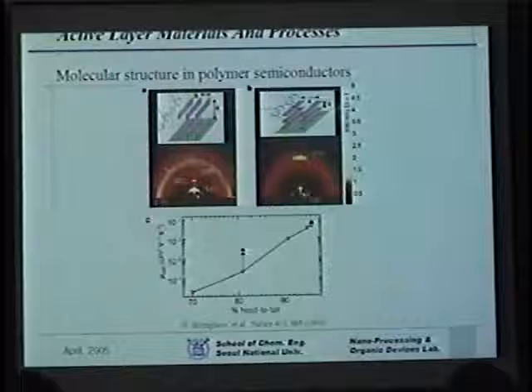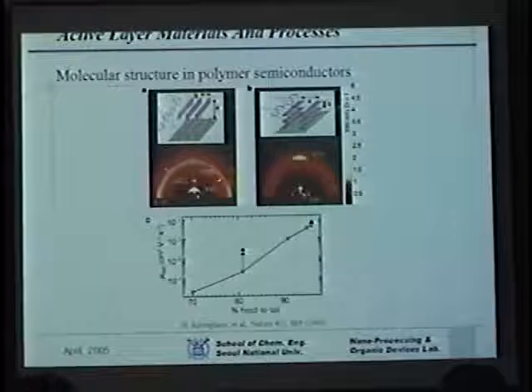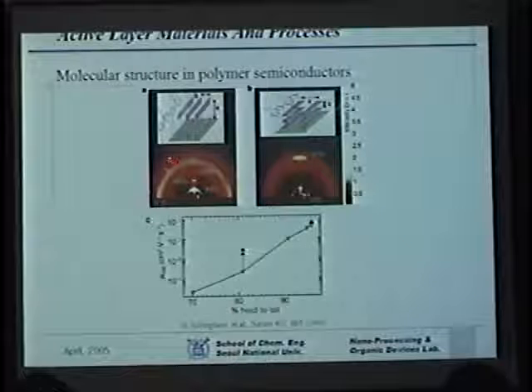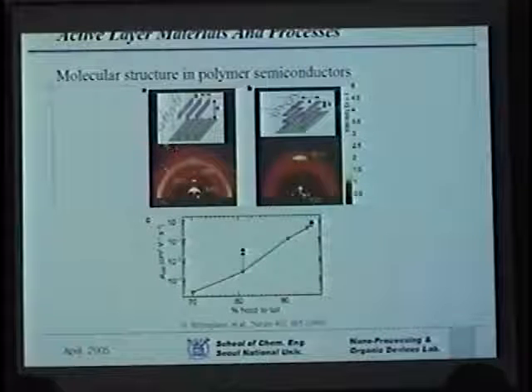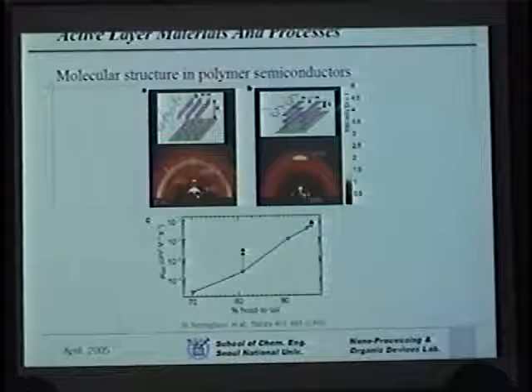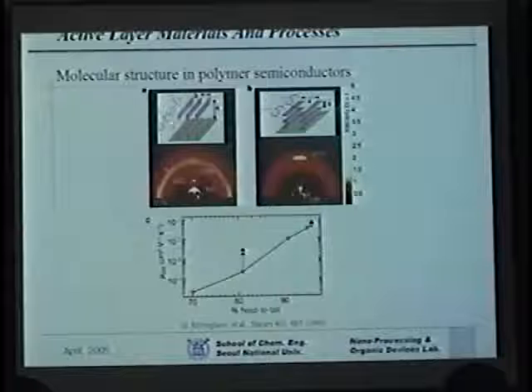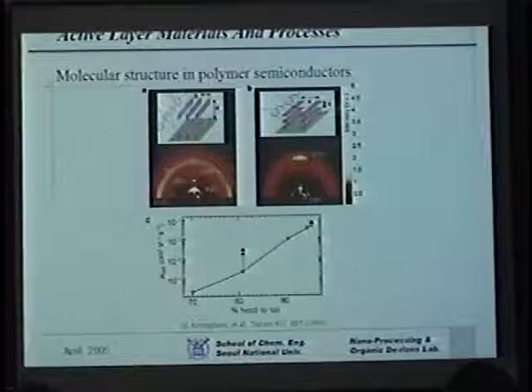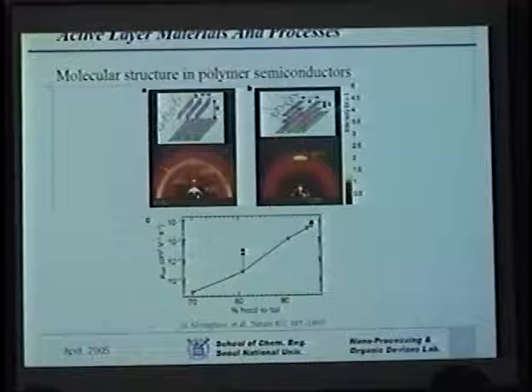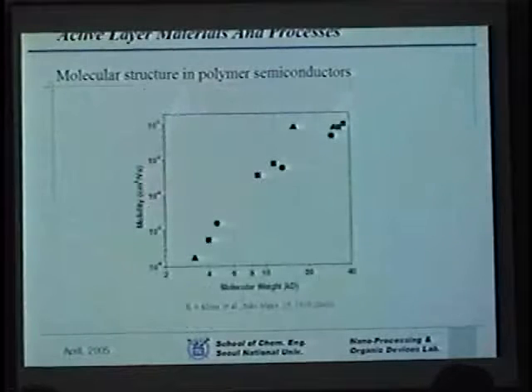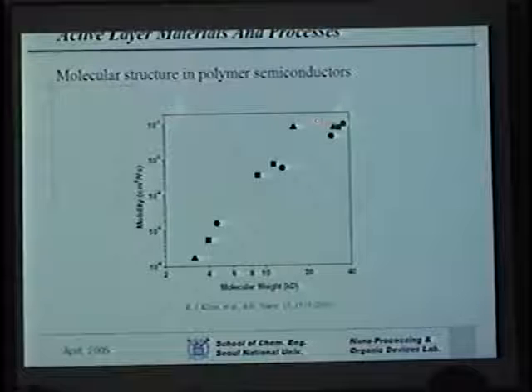Also shown here is the effect of molecular structure in the case of polymeric material. And it has really to do with the regularity of the molecule. For instance, if it's aligned this way, and the pi bond here overlaps with that one, there's a natural conduction path here so that electrons can flow fairly well this way. But if it's stacked this way, the overlap is in this direction and the electrons travel this way, so that you eventually have a lower mobility. And with the polymer semiconductor, the highest mobility is in the range of about, as indicated before, 0.02.